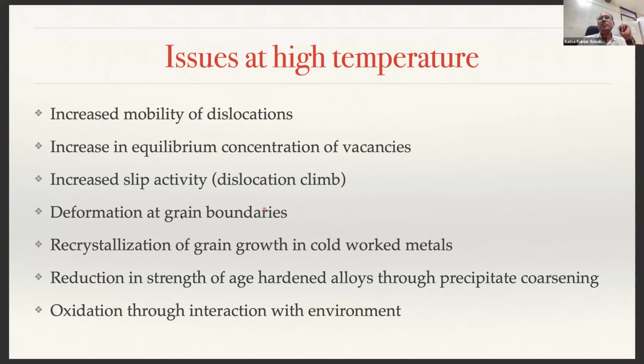And usually you have the grain boundaries which will act as an impediment to dislocation motion. At these high temperatures, the grain boundaries being the weaker spots, are going to become even weaker, and hence whatever resistance the grain boundary used to offer, it will not be able to offer. So that means the grain boundaries themselves will deform.